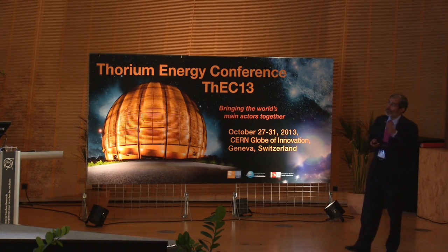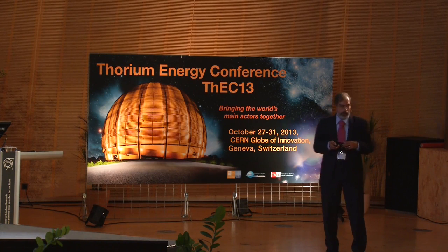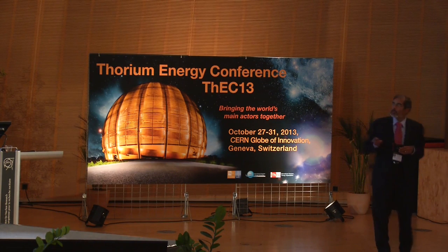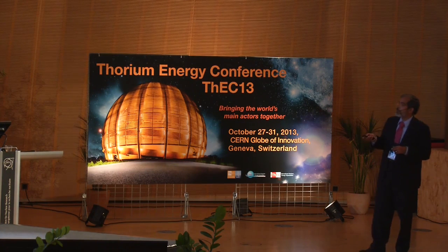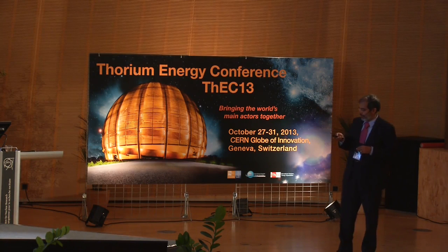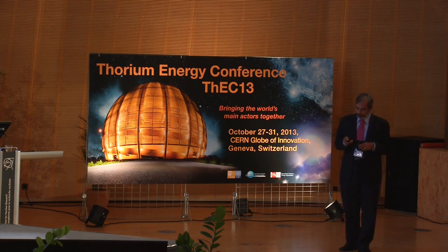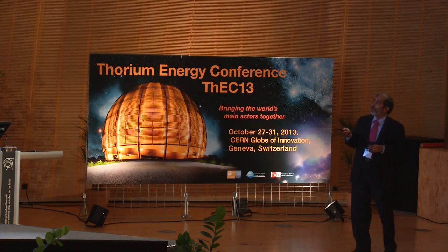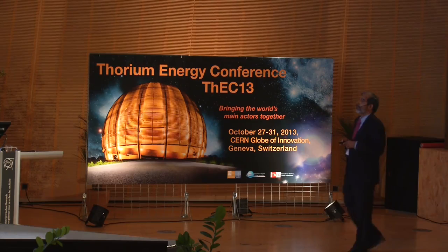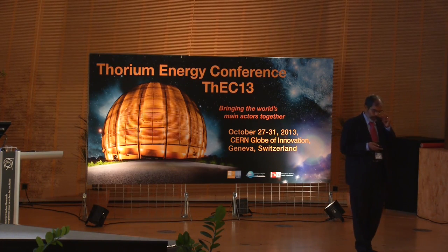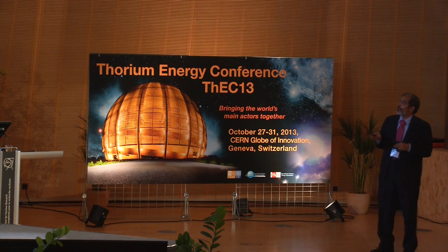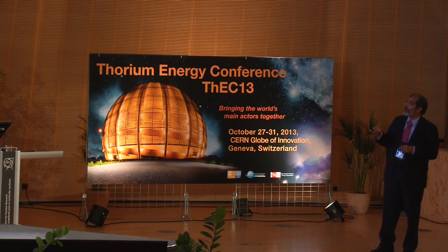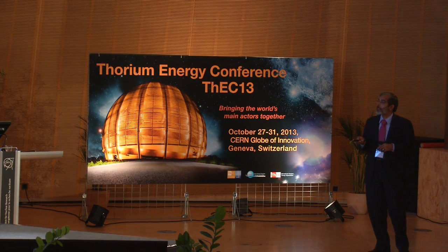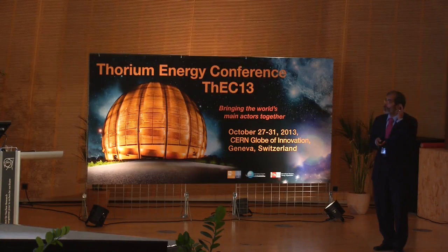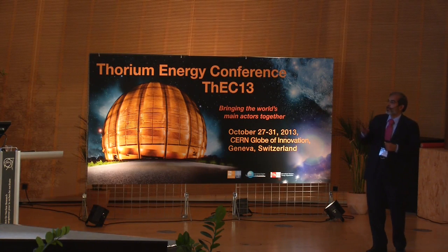So we have now started looking at the various molten salts and how to operate them under natural circulation conditions. Some of these facilities have been established. A molten salt corrosion test facility to study the material compatibility has also been established. And here is a comparison of this molten salt fast breeder reactor and molten salt thermal breeder, where we use the fuel salts, and the main difference is that the fissile inventory for metallic fuel fast breeder reactors is very high. In fact, these are not our studies, it's just from the literature.